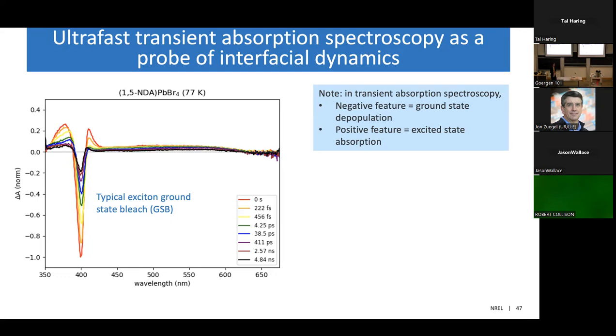Right? So here I have the transient absorption spectra for one of the perovskite compounds. And frankly, the TA spectra for a lot of perovskites are kind of boring. You just see a really strong exciton ground state bleach that tells you they're leaving their ground state. But in addition to this ground state bleach, we also see a broad photoinduced absorption feature at long wavelengths beyond the bleach.